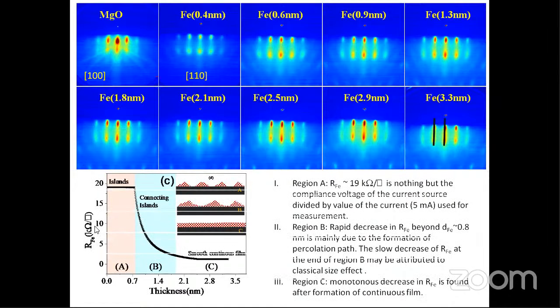This is the sheet resistance as a function of Fe film thickness. Up to 0.8 nanometer thickness, the sheet resistance is almost constant. This is because at low thickness of Fe, the film is in island form, and there is no path for electrons to flow from one contact to the other. That's why the sheet resistance is almost constant.